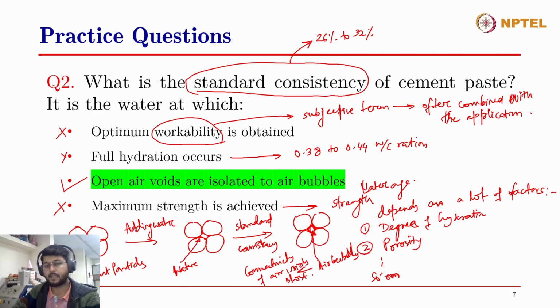Now what happens when the connectivity of air voids is lost? Now that the water has surrounded the air voids and they have turned into air bubbles, there's a lubrication layer between the air voids and between the cement solid particles as well. This lubrication water within the solid particles is able to make the particles move around. So that provides us with consistency, and it also increases the level of compaction inside the paste. So this is the water content.